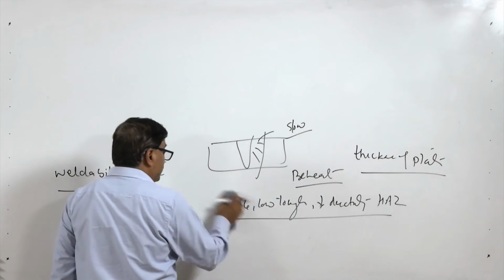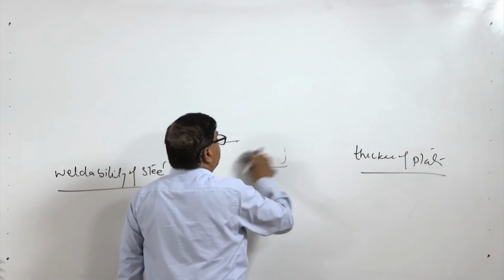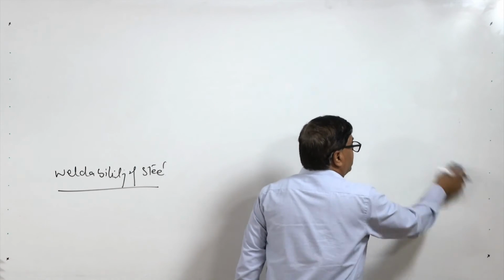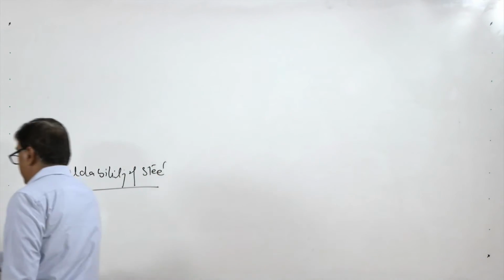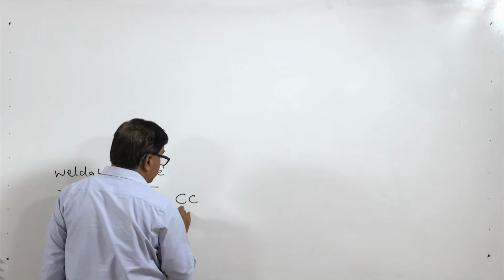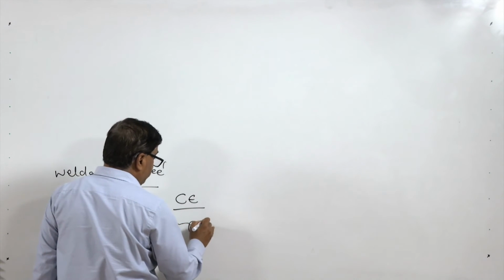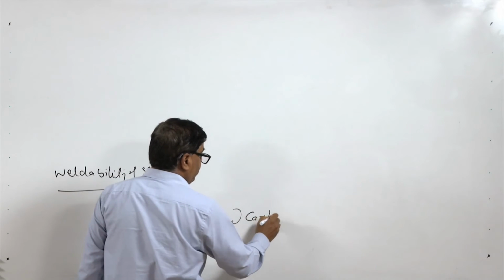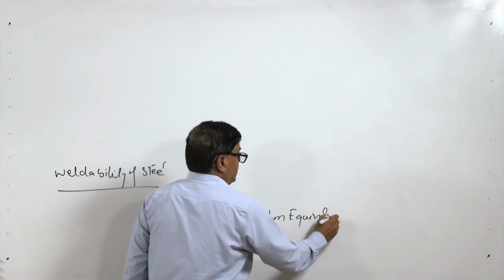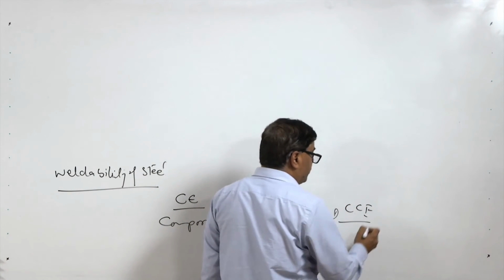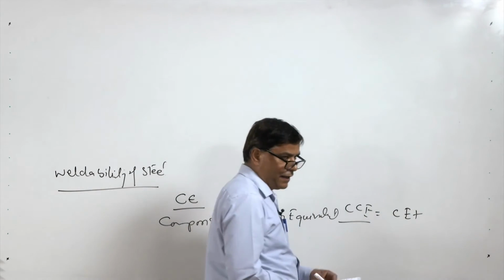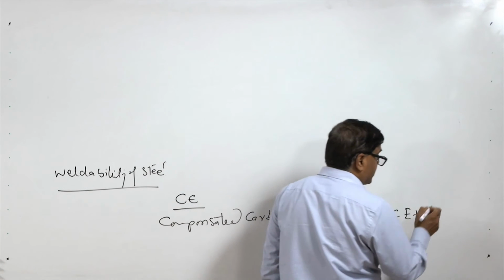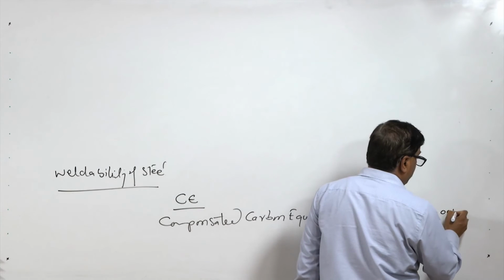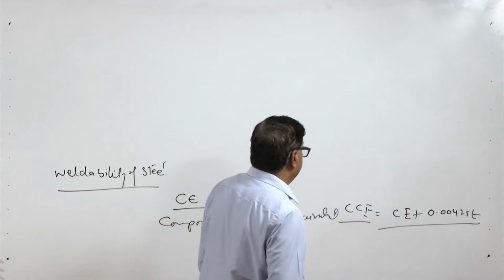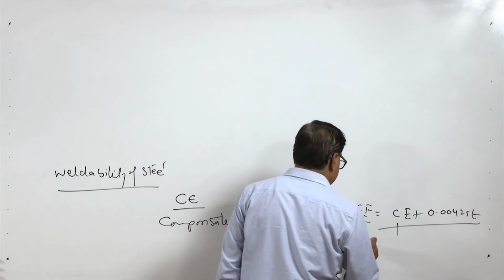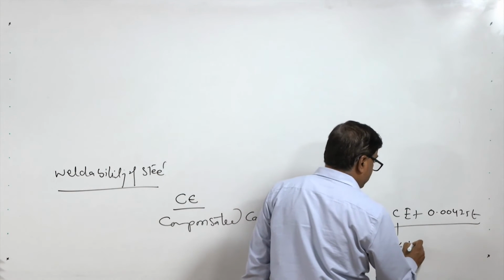That is why, in addition to the carbon equivalent, sometimes the thickness of the plate is also considered for determining the possible hardenability or the cracking tendency. So, for that purpose, instead of using just a carbon equivalent term, one additional term, the compensated carbon equivalent, is calculated. This is written as CCE, compensated carbon equivalent, which considers the normal carbon equivalent as it is, plus the thickness parameter, 0.00425 T. So, this is an empirical equation which considers the thickness of the plate. CE stands for simple carbon equivalent and T is the thickness of the plate in mm.